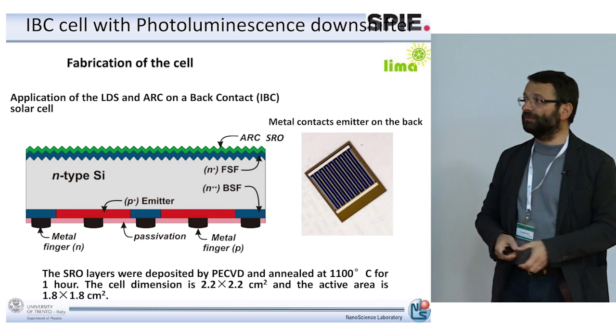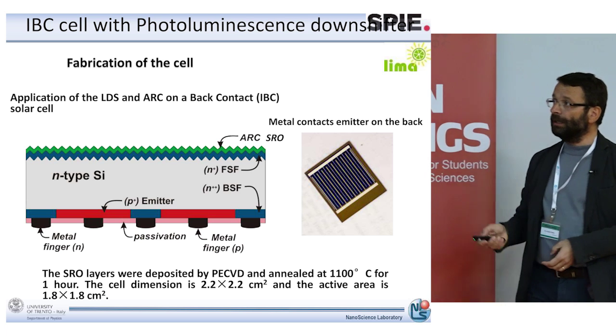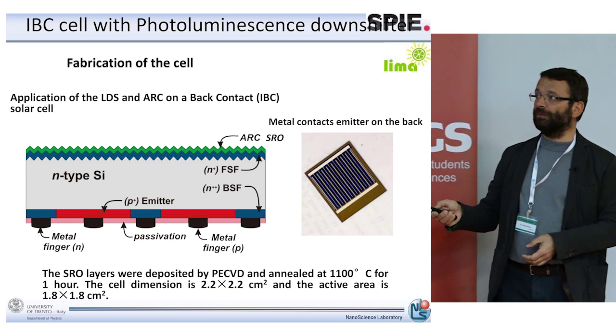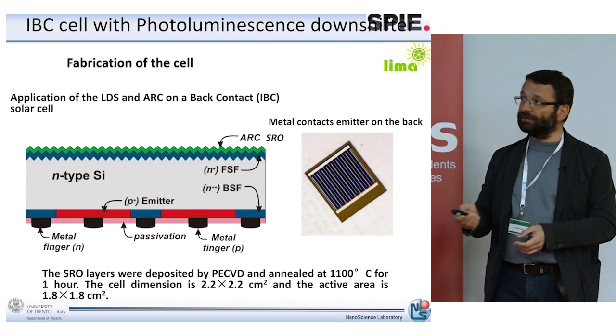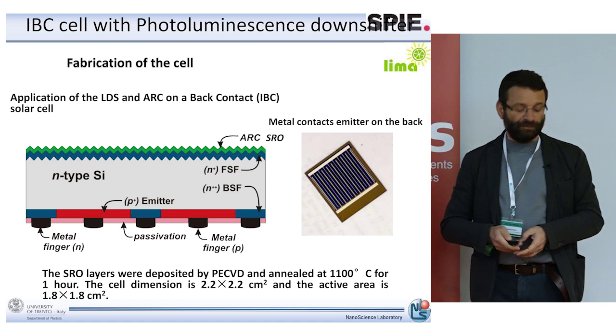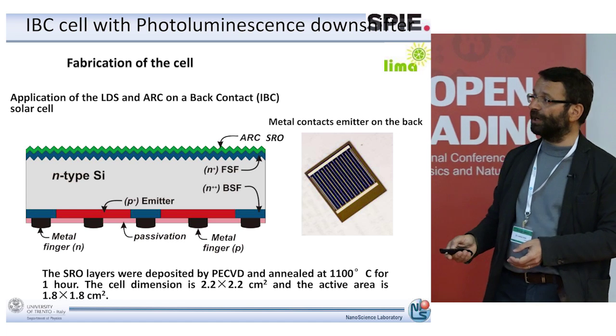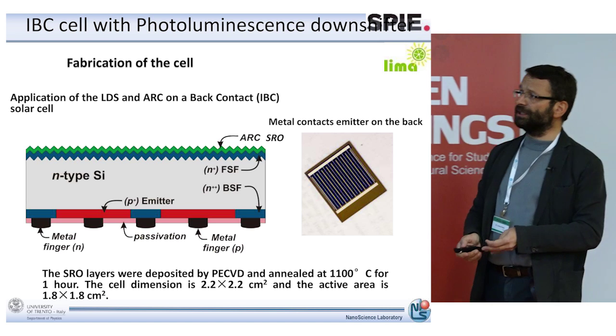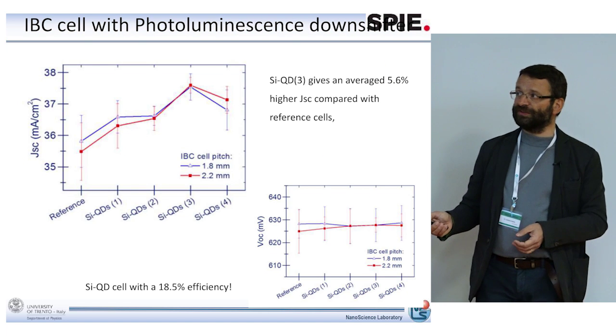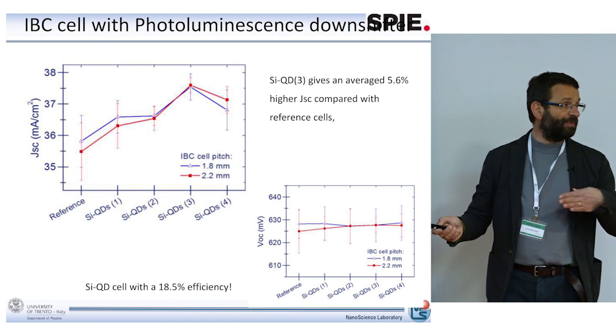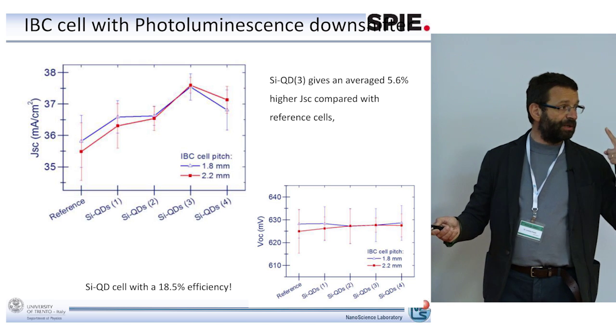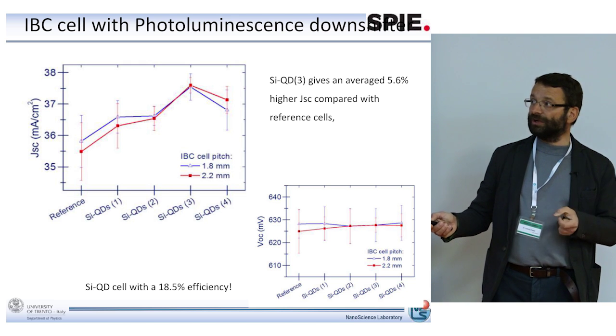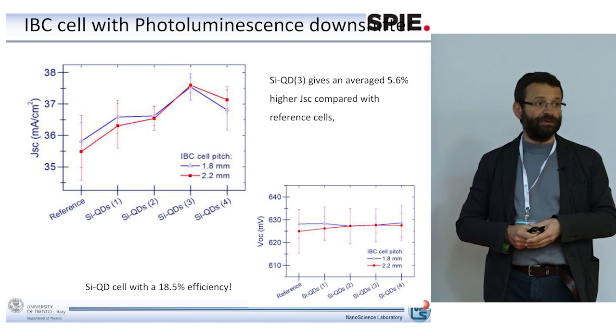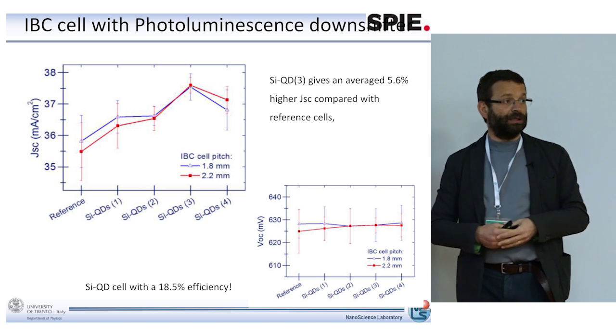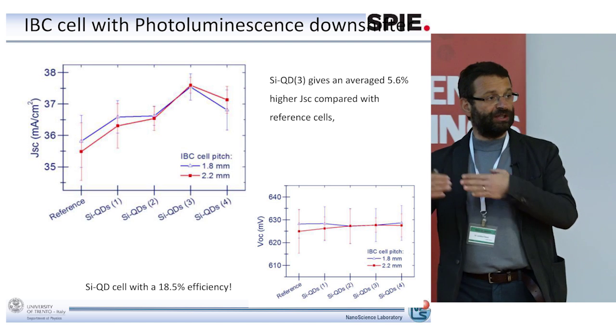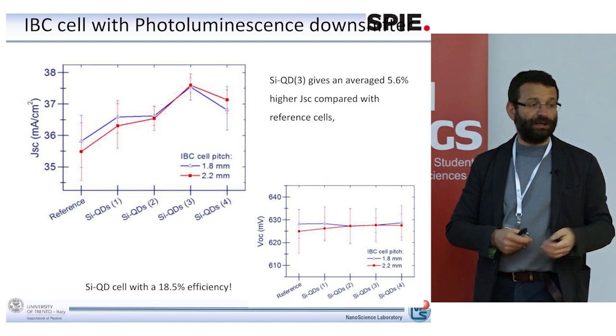Here is a photo of the cell on the back side of the cell. And then we compare a cell with the nanocrystals with a cell without the nanocrystals, but with an anti-reflection coating made by silicon nitride. And those are the results. Here is the open circuit voltage, and what is very important is that the presence of the nanocrystals does not change the open circuit voltage, which means that the surface passivation is essentially the same with and without the nanocrystals.